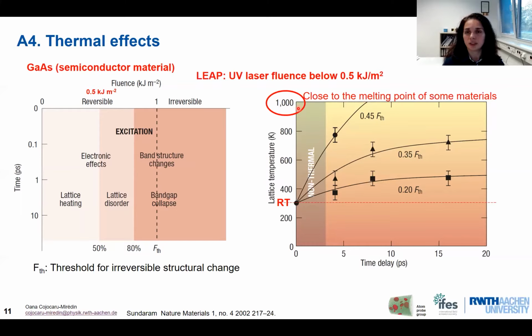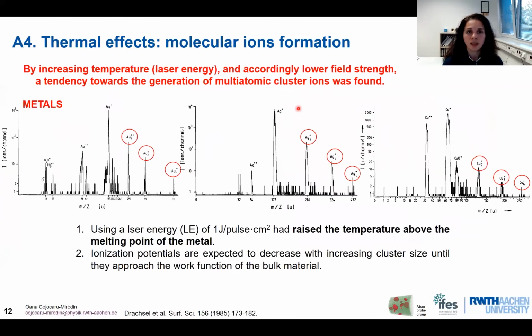And this is definitely a temperature which approaches the melting point of some semiconductor materials. So definitely this is something that we want to have not happen inside our atom probe experiments. Now there is a very old work done by Drachsel in Germany, where they have shown actually that when we reach these very high temperatures, melting temperatures, we might have the formation of molecular ions on the mass spectra.